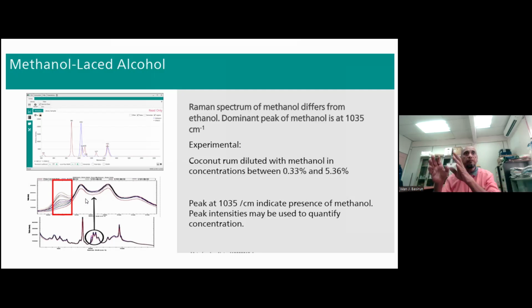So you identify the molecule you want to analyze, and you get the Raman spectrum or FTIR. Now, when you have contamination and you run the Raman spectrum again, you have the overlap of the spectrum of the molecule you want to detect with the contaminant molecule. For example, if I have both ethanol and methanol in the same sample, whereas I only want to detect ethanol, I should get this spectrum, this wavenumber here. And if I want to detect methanol, I should get this double peak here.